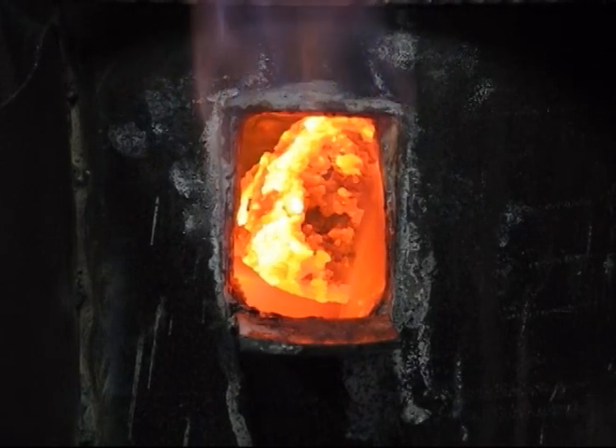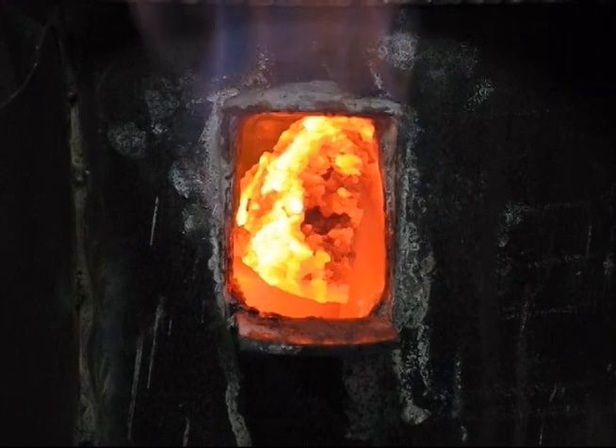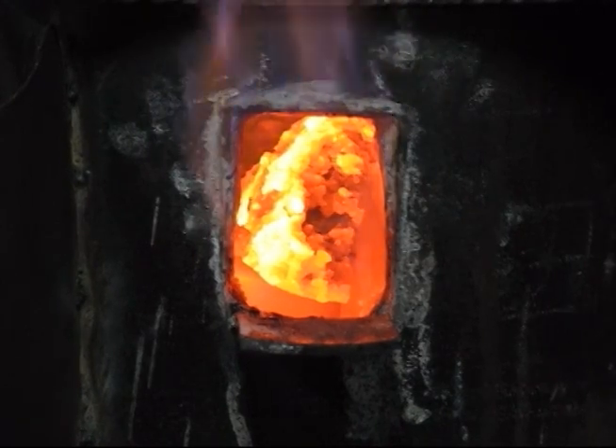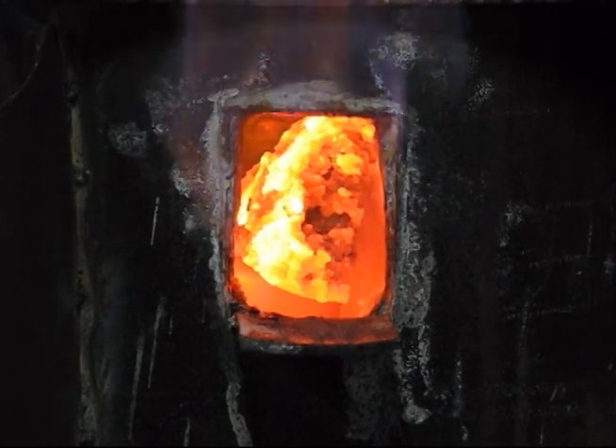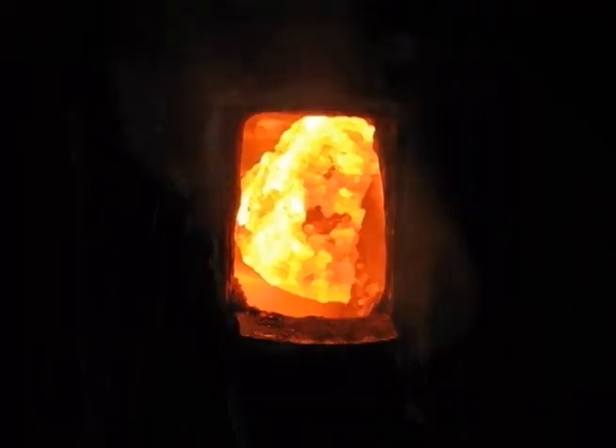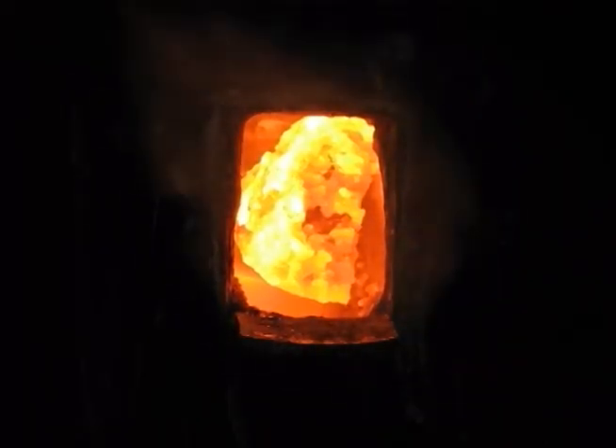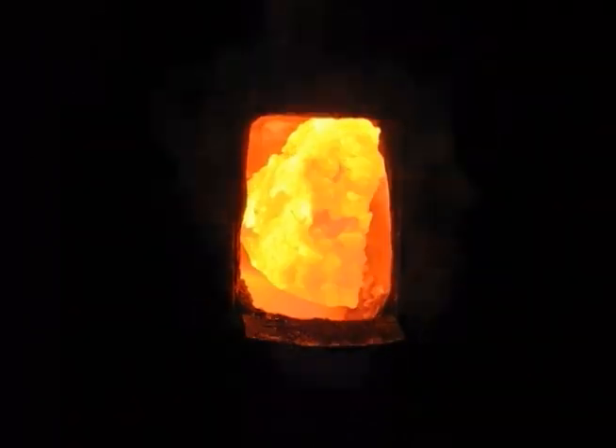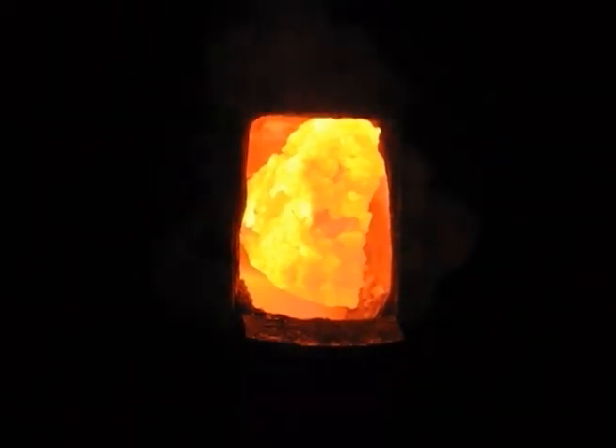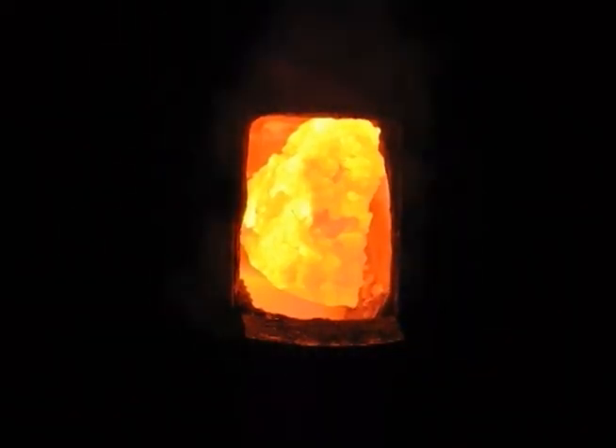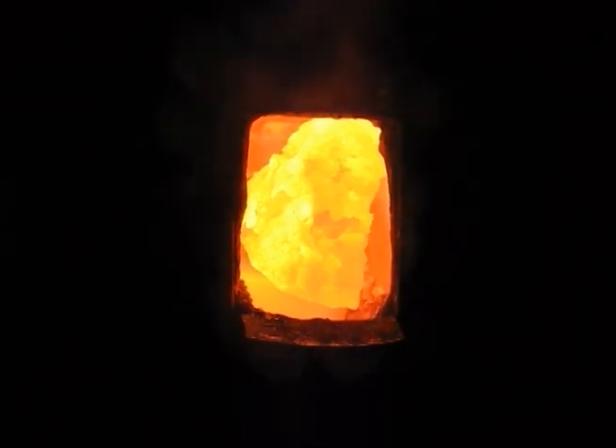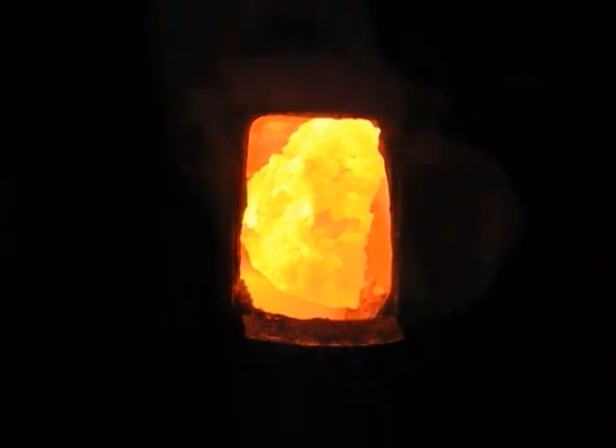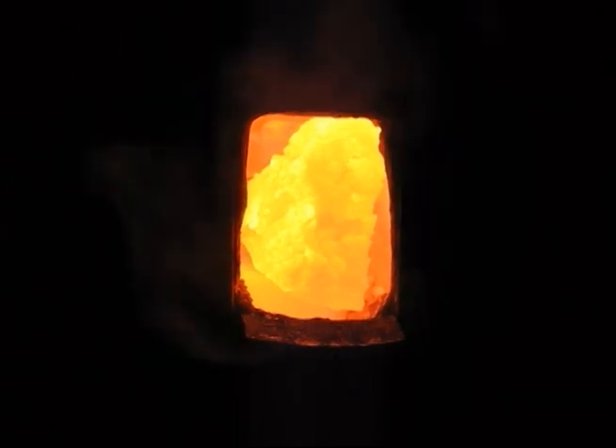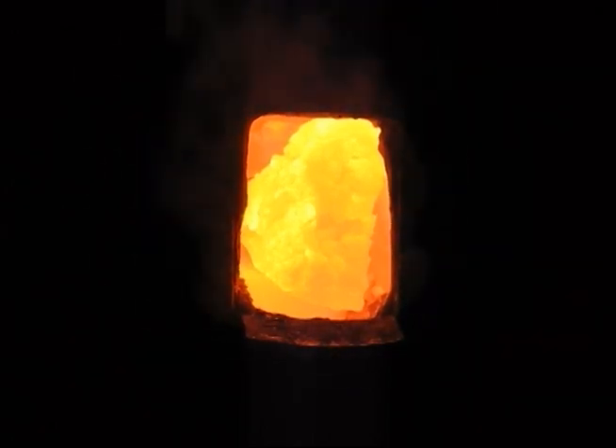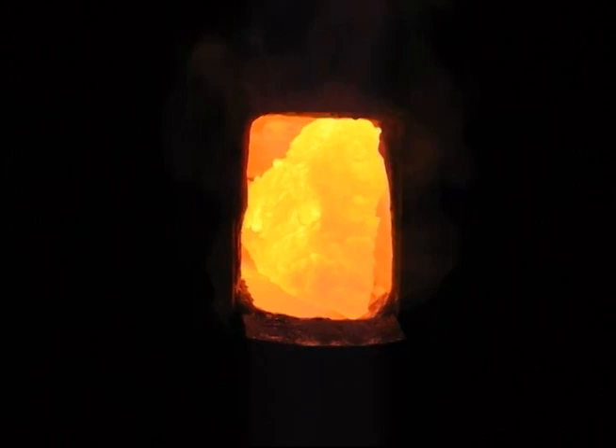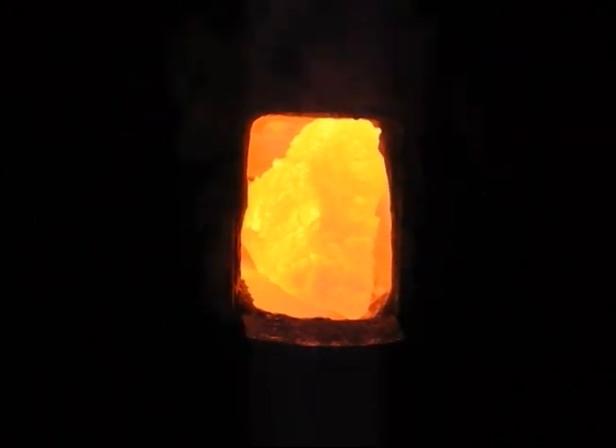The forge is fired and the bloom is placed inside and allowed to reach welding temperature. Patience is important, as such a large mass will take time to get hot enough. As the metal gains temperature, its color changes, reaching a bright yellow when it is ready to be forged. Just before that happens, the slag becomes molten and takes the appearance of liquid butter. It bubbles and drips from the surface of the metal.